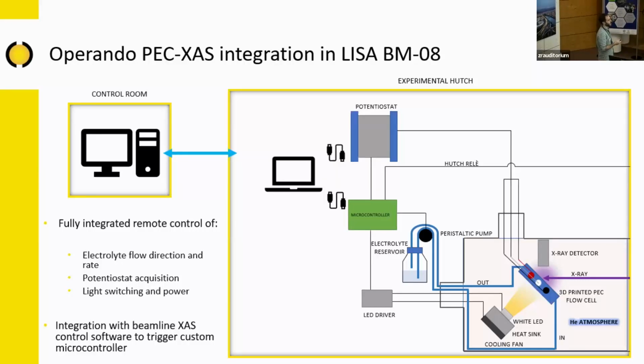We designed a setup that is able to be controlled directly from the control room without touching anything in the experimental hutch during the experiment, by simply interfacing with a microcontroller that is controlling both the potentiostat and the LED driver. So we have bias and illumination controlled by this microcontroller, directly interfaced with the control room workstation. And then we also have the control of the flow system, the flow of the electrolyte in our system, as we'll see later.